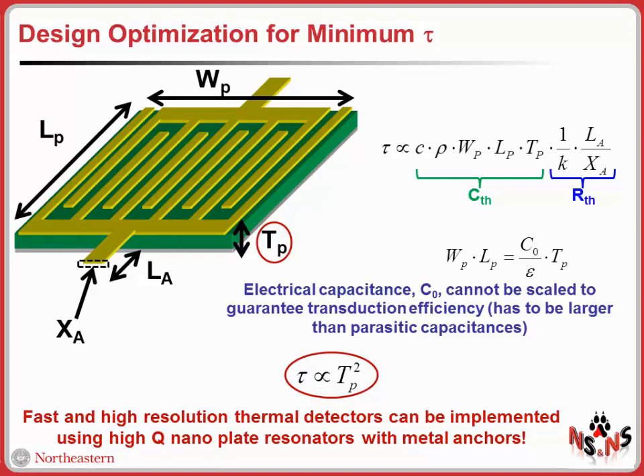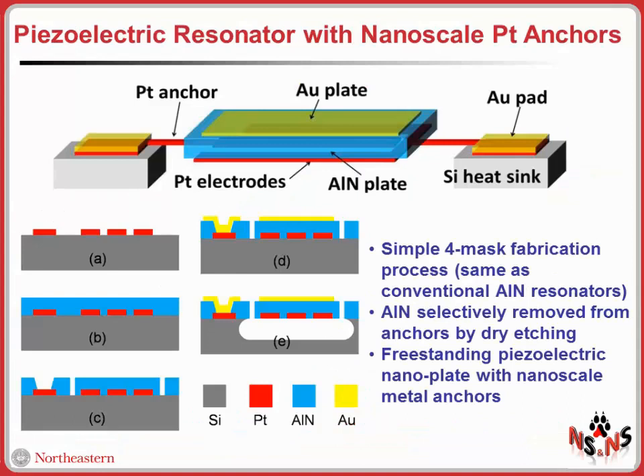So based on these simple ideas, we developed a fabrication process that can selectively remove the piezoelectric material from the anchors, as you can see here. So the device is composed of thin film aluminum nitride plates, typically between 500 nanometers and 50 nanometers, a platinum electrode on the bottom, and another metal electrode on top, and I will talk a little bit more later about how we can get infrared absorption in this kind of devices. But you see the device is anchored to the substrate only using these platinum metal anchors.